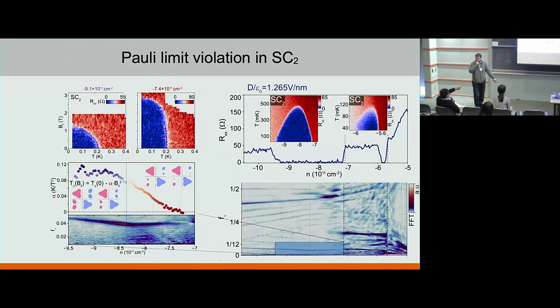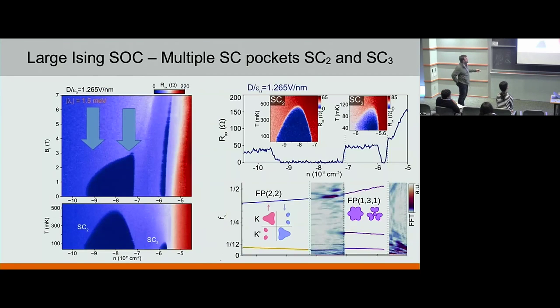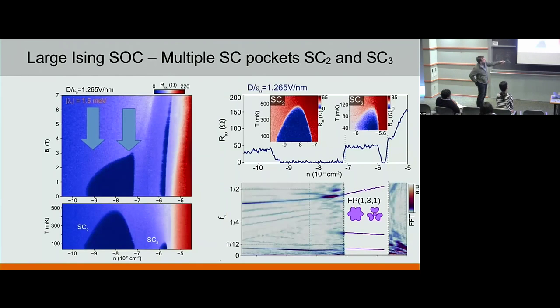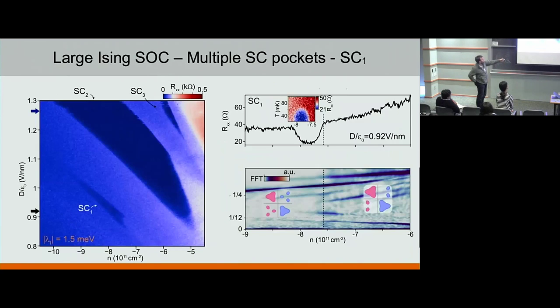But the field I need to kill the superconductor on the left half, was that bigger? No, it's smaller. Okay, so it's consistent with this value of alpha being large. Yes. And the other thing is all the superconductors you see have one end of them connected to a Fermi surface changing transition, is that right? Let me confirm. I tend to say yes. So definitely these two, and also the first one as well. Although sometimes this change is a little bit fuzzy, more fuzzy than when there's a rise in TC. But it's close enough.